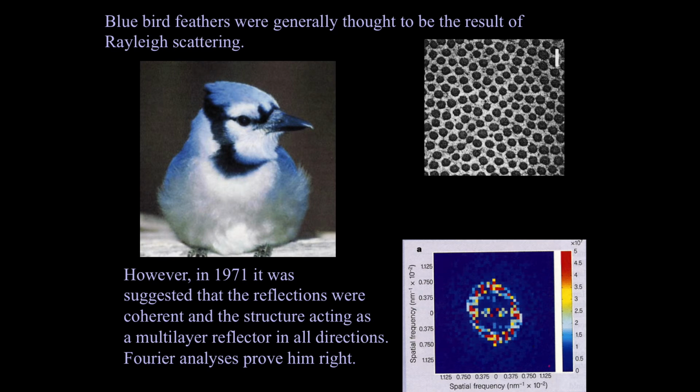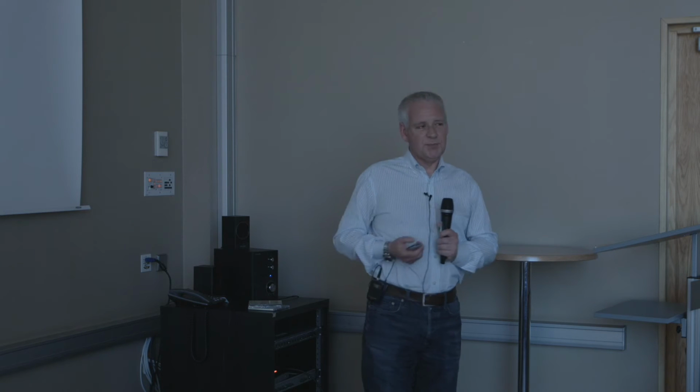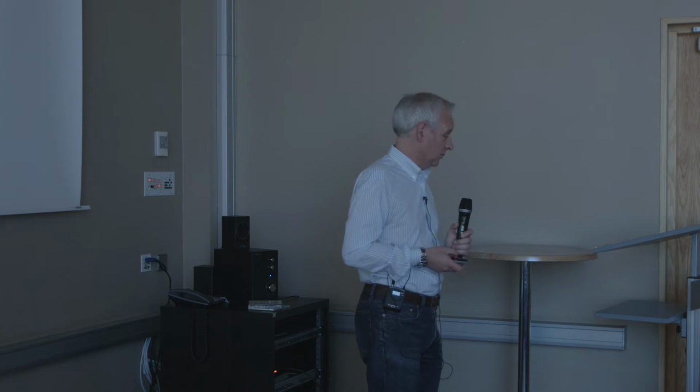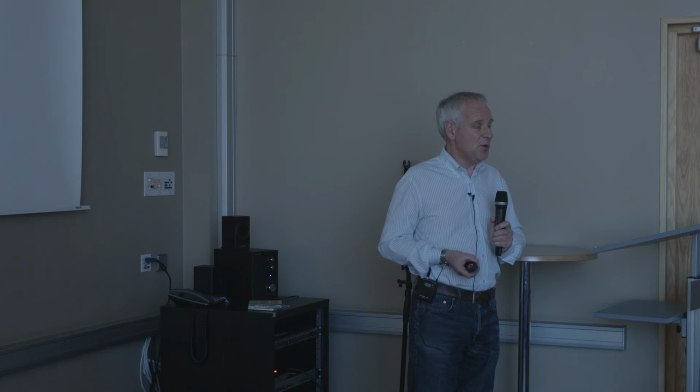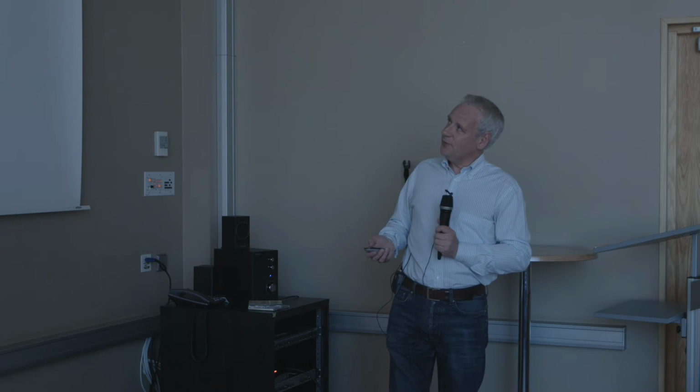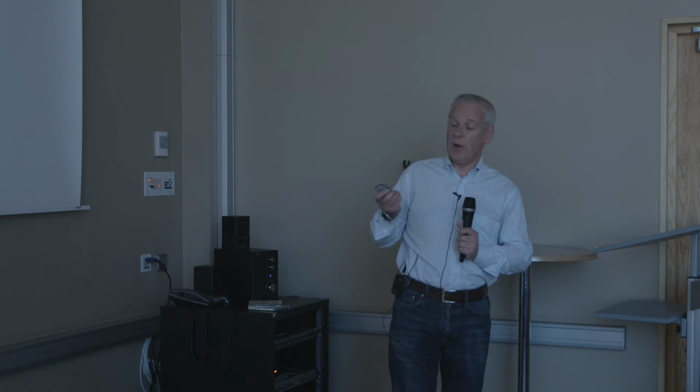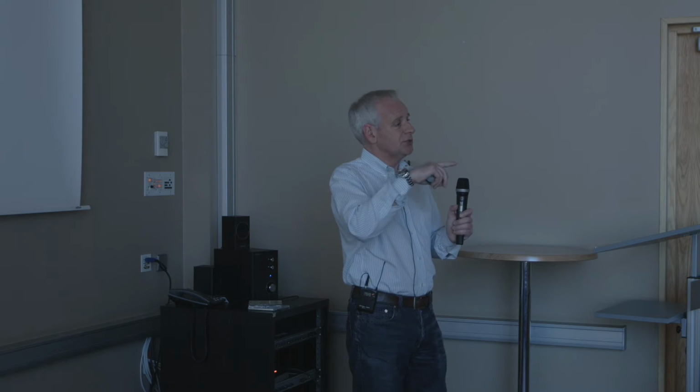Blue actually is a colour that's turning up a lot in nature, and we've only just realised it. We're just putting out the paper now, actually, that the reason for this is that it's really easy to evolve. Red is one we're having problems with, but blue is all over the place in nature. And in fact, it's because it's not a narrowband colour after all. We first thought that blues in nature were the result of Tyndall or Rayleigh scattering, where the longer wavelengths just miss the structures and the shorter wavelengths hit them and get reflected. So you get a lot more reflection of the shorter wavelength blues than the longer wavelength reds.